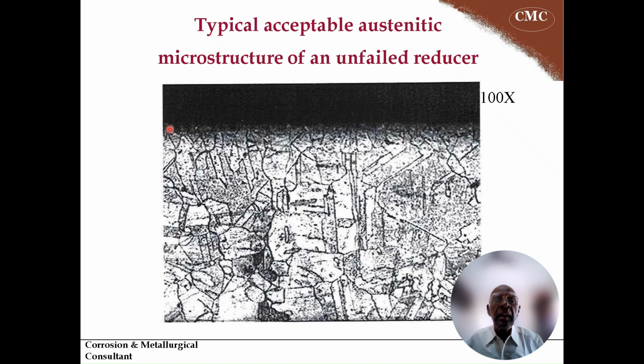So what you see here is the typical austenitic microstructure of the 800H, which is a nickel-based alloy with austenitic microstructure, and this is the typical acceptable structure. We call it the austenitic step structure. You can see annealing twins and slip bands, and this is an acceptable structure. This is also taken from one of the reducers which is being used.